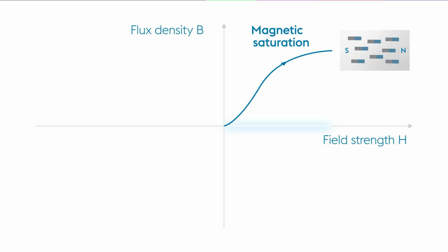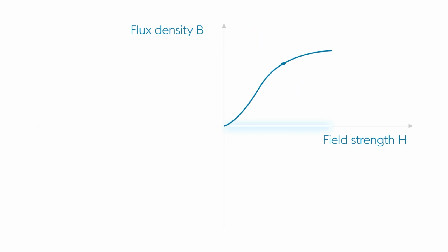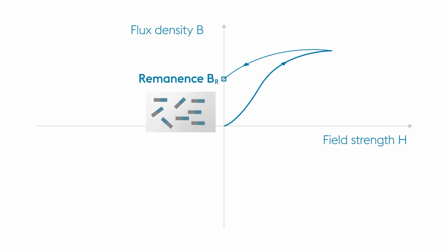This initial alignment takes place along the so-called initial curve. Now I reduce the current. The point at which no current is flowing is when the field strength becomes zero, but not all dipoles will face in the same direction. Residual magnetization remains in the electrical steel strip, and this point is called remanence.